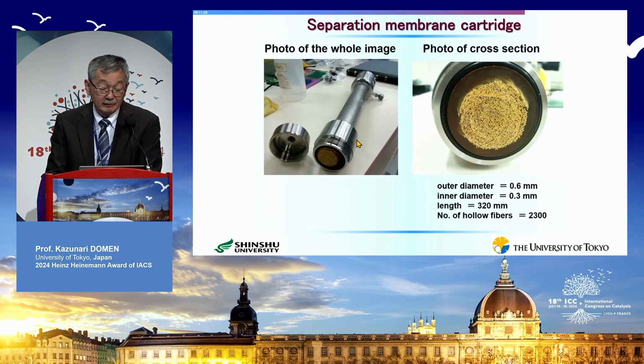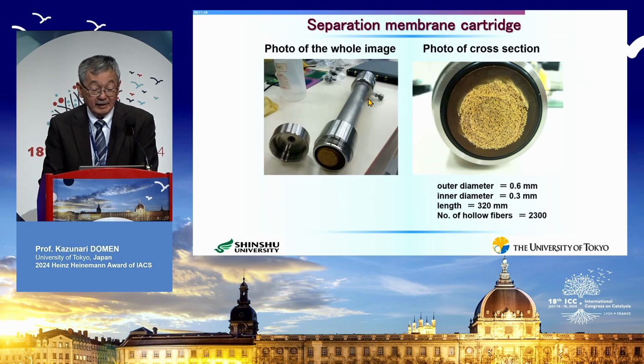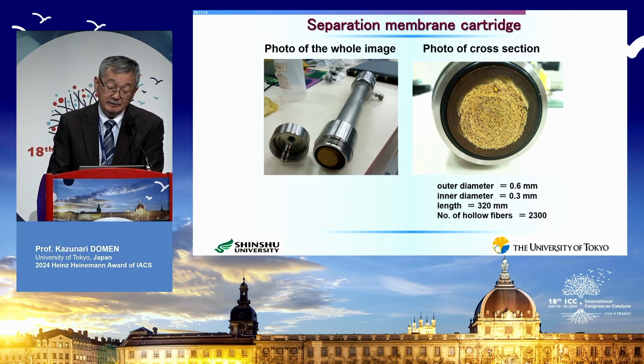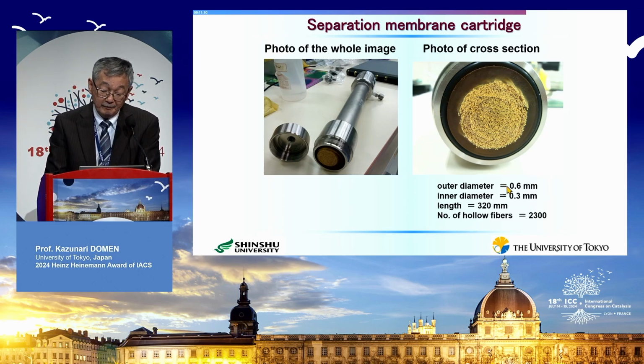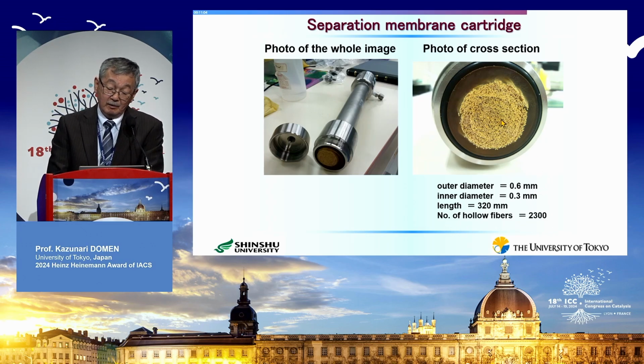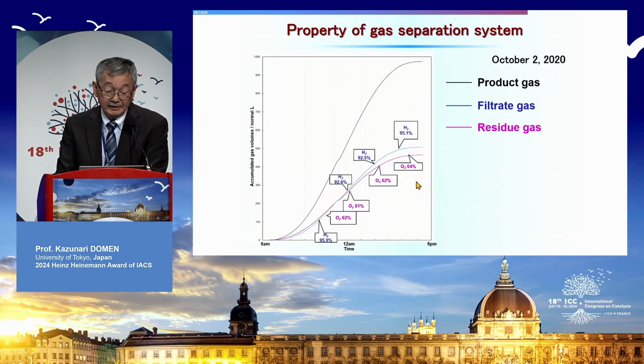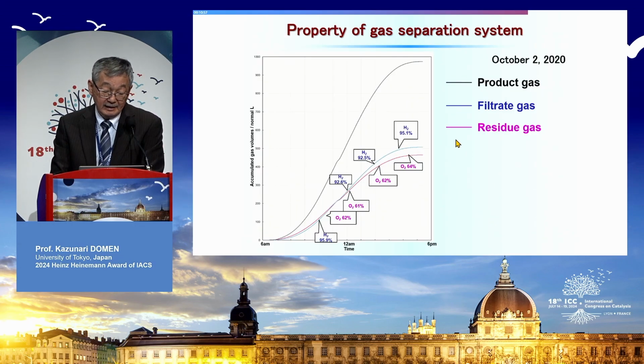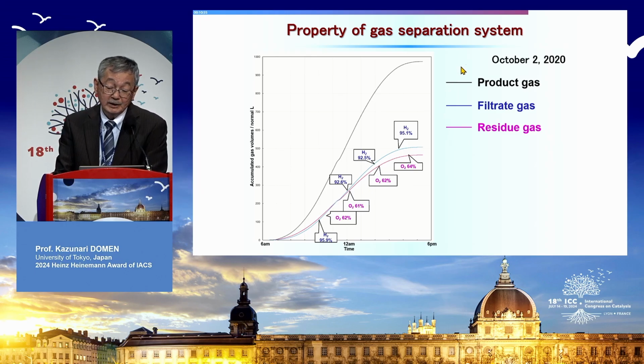And this is a photograph, and the length of this cartridge is 32 centimeters. The inside of this membrane cartridge is filled with hollow fibers. The number is 2300, like this one. And the inner diameter of this hollow fiber is 0.3 millimeter. Using this cartridge, we carried out a one-day experiment for separation of the hydrogen.